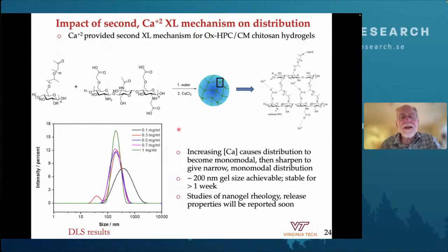What he found was that as he added increasing amounts of calcium, the distribution went from multimodal in DLS to monomodal, centered between 100 and 200 nanometers. So indeed, that worked very well. The dual cross-linking methodology allowed us to use both polymers, water soluble, no acetic acid, to generate a nanogel dispersion. We're pursuing the use of that nanogel dispersion for delivery of active molecules and other applications.